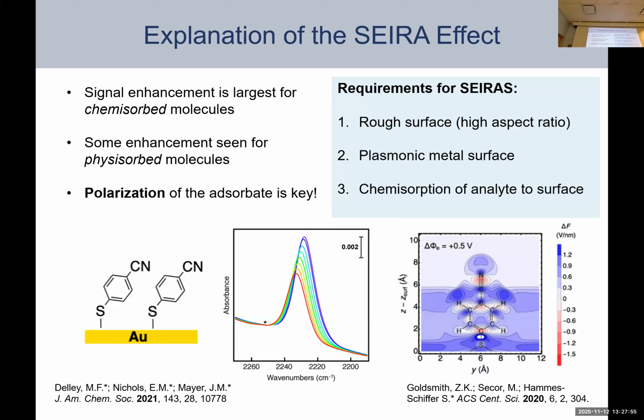Okay, so to summarize that, the signal enhancement in SEIRAS is actually largest for chemisorbed molecules. You can see some enhancement for physisorbed molecules, although it's less. And the biggest important aspect here is polarization of your adsorbate. Now, what do you actually need for SEIRAS? So you need a roughened surface. I think this is very much agreed upon. So think of high aspect ratio, sort of like spikes or little nano daggers on the surface, that's best. Having a very pristine, really smooth, extra clean surface is terrible for SEIRAS.